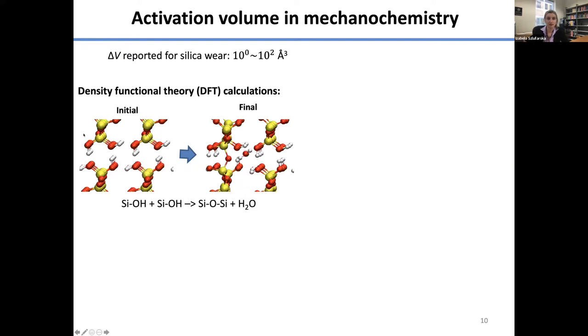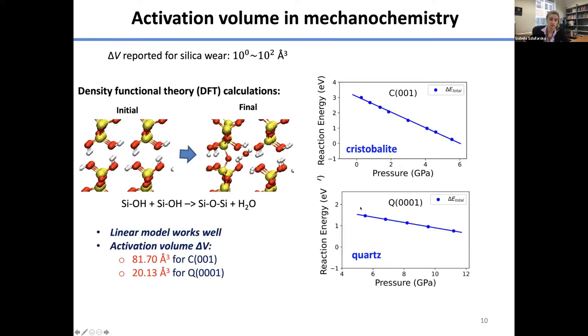And so we perform these calculations for different kinds of silica surfaces. So here are just a couple of examples showing cristobalite and quartz. And this is the reaction energy as a function of pressure. It's a linear function, so it's consistent with the models I've been showing before. And from the slope of these, we can get the activation volume, which is really the coupling of the chemistry to mechanics. So when we extract it in these particular cases, we get values of 20 or 80 angstrom cubed. And if you compare to experiments, it agrees well with experiments, right? But it's not that hard to do because in experiments, the range is two orders of magnitude. So it's not particularly impressive.